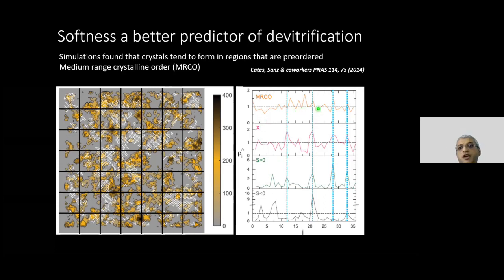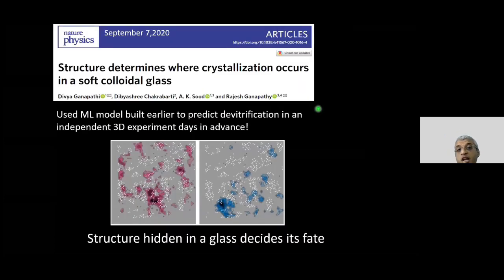Okay. Now we can do one thing more than what we've done so far. We can take another glass sample in which we don't analyze anything at all in the dynamics. We are just going to take the machine learning protocol that we developed earlier. We are going to look only at structure and try and see if the ideas that we had earlier can predict. And this is once again what you're seeing: these are soft particles, these are hard particles, and you see that crystals predominantly emerge in regions with a very high softness.